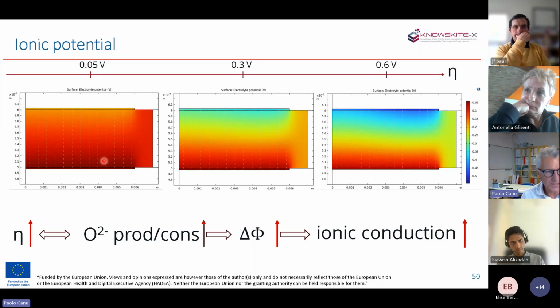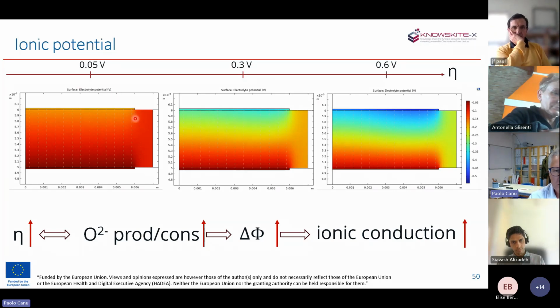The model can predict also the distribution of ionic potential, and that's already a sensitivity analysis on the overvoltage. And you see that that's a magnification on the electrode, the cathode and anode on both sides. And you see the distribution simply by color that tells you the difference in potential. At increasing overpotential, their gradients are larger and larger. And of course, if the gradient of ionic potential in the cell is increasing, you would expect a much higher stream of ions through the cell.